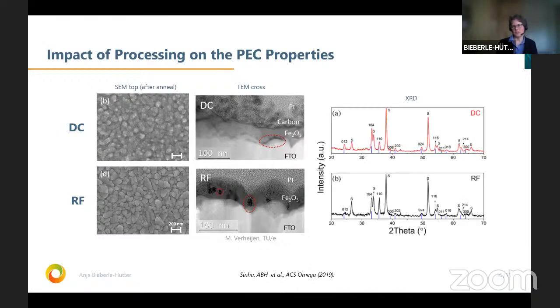From the XRD, we see that we get indeed in both cases the Fe2O3 phase. And they look rather similar, even though we see a slightly different crystal phase formation texture with the 104 and the 110 reflections. Here the 104 is higher than the 110, while for the RF, both 104 and 110 are rather similar.